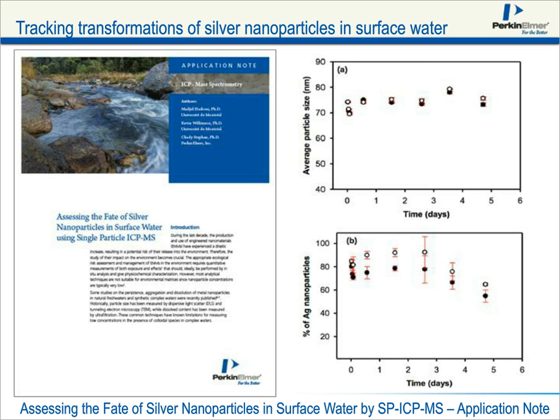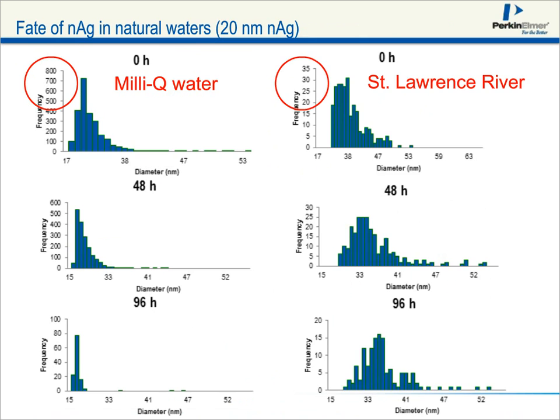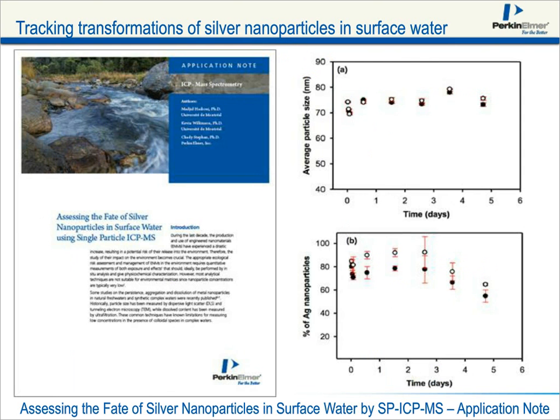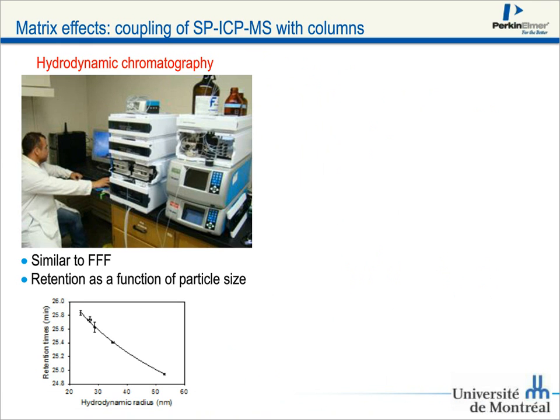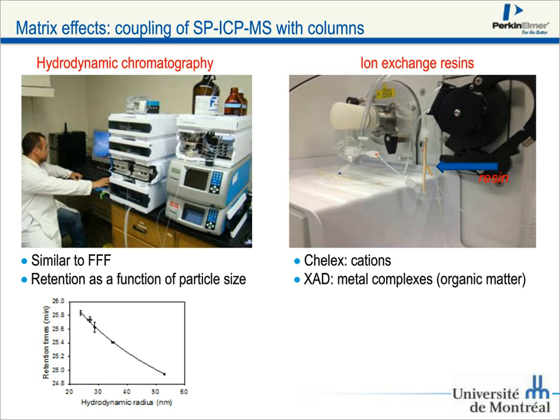But what I'd like to do in the rest of my time is to show you some of our newer results, some of the new work we're doing to try and get rid of some of these matrix effects. If you couple your ICP-MS, or your single particle ICP-MS, with different kinds of columns. In our case, we're using hydrodynamic chromatography. This is really similar to FFF, where the retention is a function of particle size. Most groups are using FFF now, but it's really the same principle.